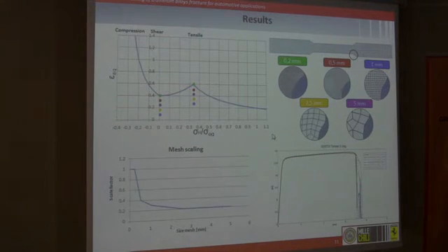The scale factor directly affects the fracture locus function. The curve is tuned in order to obtain from the analysis the same displacement at load drop-out of the experimental curve. With this method, it's possible to use the same material card in the sub-assembly models or in full vehicle models at any mesh level.